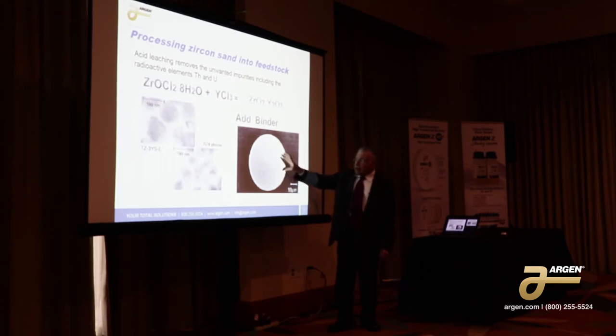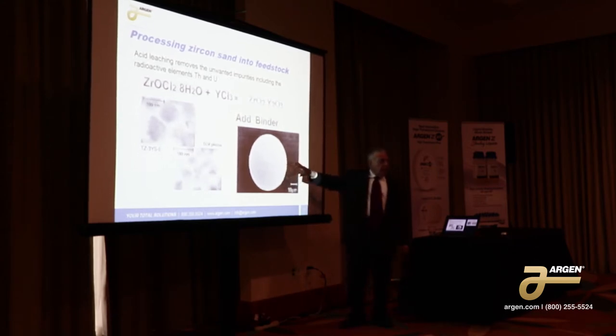You take the material and pass it through a very high volume, hot air. The water evaporates and you're left with the acrylic-bound zirconia. This is an extremely efficient process for pressing. We hydraulically press it and then we isostatically press it. The hydraulic press forms the shape and the isostatic press makes sure the disc is uniform in density from one side to the other and top to bottom.